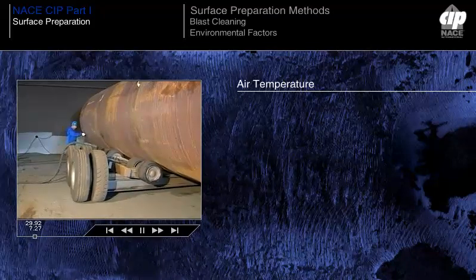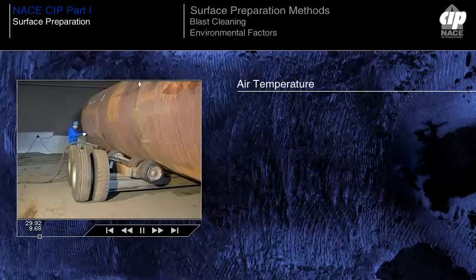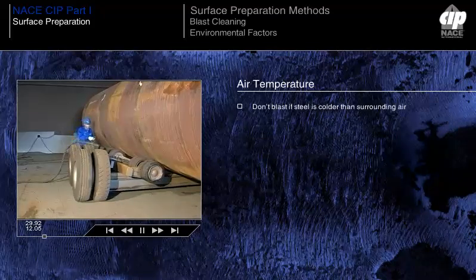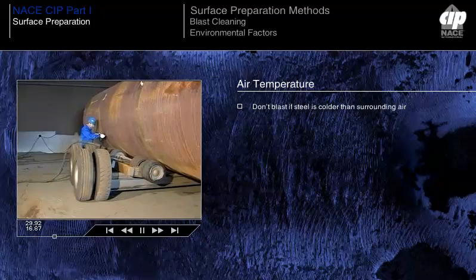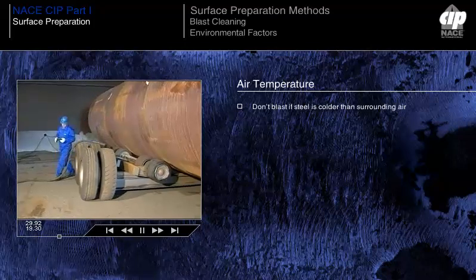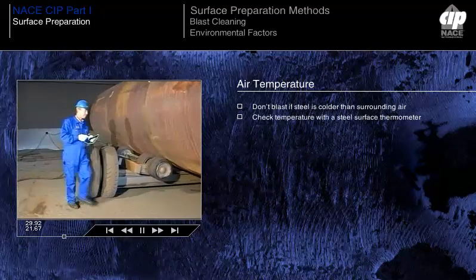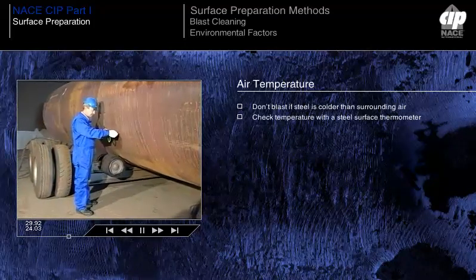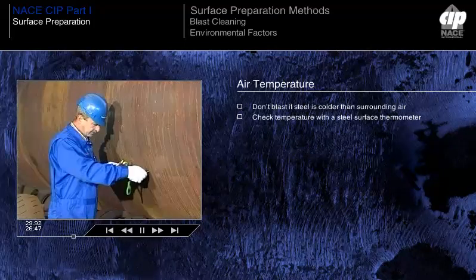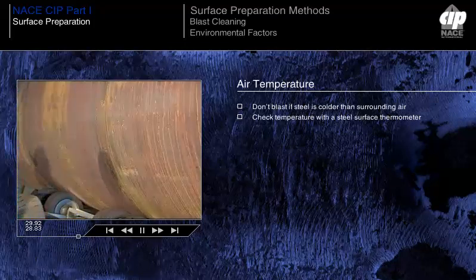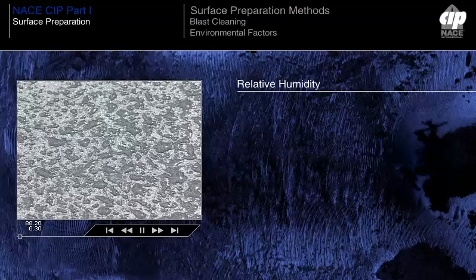It is unwise to abrasive blast if the steel surface is much colder than the surrounding air. Moisture may condense on the blasted surface, causing the surface to flash rust. The substrate temperature may be checked using a steel surface thermometer. When blast cleaning, high humidity, moisture, can result in rapid deterioration of the cleaned surface.